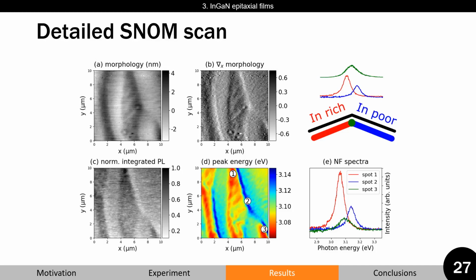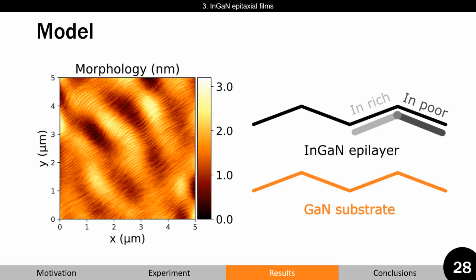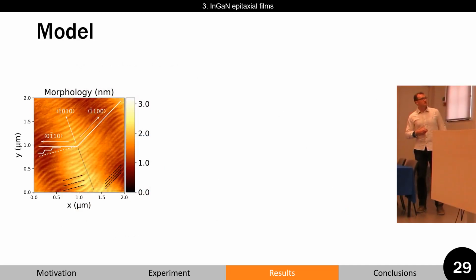To understand the origin of different indium incorporation on different slopes, we decided to look at the template on which the epilayers were grown. This is an AFM scan of a large area of the gallium nitride template. One can see these monolayer step edges form. If we zoom in on this map, we can identify different crystallographic orientations and notice that there are two different slopes. One slope is aligned with crystallographic orientation, and the terrace width, or distance between step edges, is narrower, while another slope, due to surface miscut, deviates from a crystallographic orientation, and the terrace width is larger.